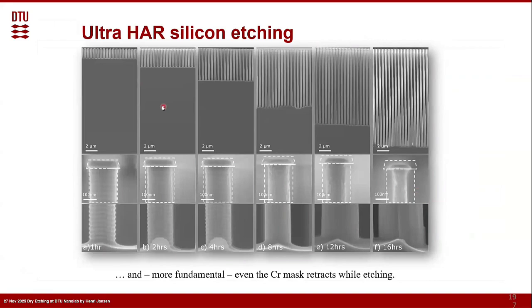Doing so, we could see that if you etch deeper, that is getting higher and higher. The structures are getting nicer, but we noticed also that, hey, the chromium is still etched. You can see a kind of a retraction even for the chromium. It's much, much, much less than resist. But if you go for the extreme high aspect ratios of 50 and more, it becomes prominent.